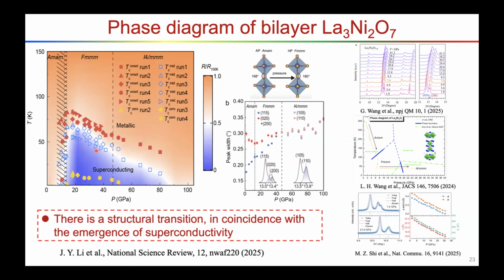for our work, in this paper, even in the superconducting state, we can still see the splitting of the two peaks. That means in this region, it's still an orthorhombic structure. And in this work from Xianhui Chen's group, they also found splitting of the peaks in the superconducting state. So there are many conflicting results.